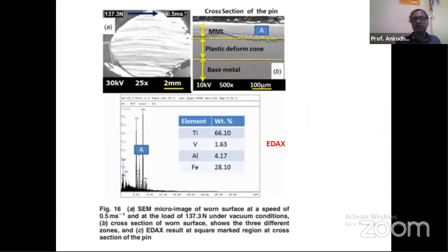Okay, I'm not going into details of all these things because there's not much time left. You can use this very same equipment to get identification of chemical species also. That is because when the incident electron beam impinges on the surface, it would give rise to characteristic X-rays. Now, when these X-rays are energy analyzed, you would get information related to their chemical nature also, similar to how we used such information for our XPS case. In the case of XPS, they were electrons which got emanated, but in this case they are X-rays. But the problem with this is that the resolution of those areas that you are trying to differentiate in terms of elements is much less.